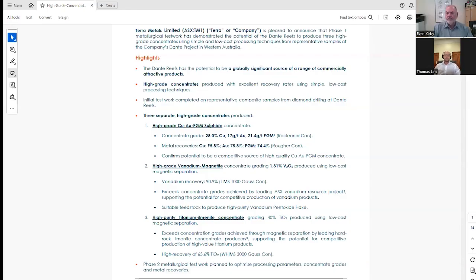It's interesting. I did a post on this the other day that the vast majority, over 90% of the titanium market actually comes from ilmenite sources. So it is the most important source of titanium globally. And I've heard a lot of people say, well, no one's mining and selling ilmenite. Well, it's not true. There are companies who are commercially producing and selling ilmenite concentrates and using the same tools that we're using so far. And as you pointed out, Evan, the simple processing techniques we've used so far have shown better recoveries using the low-cost tools to a higher grade concentrate than some of those producing companies who are exporting their concentrate. So I think it's an amazing initial result and very exciting. And as I said earlier, it clearly positions the project as a potential competitive producer on these three different concentrate products.